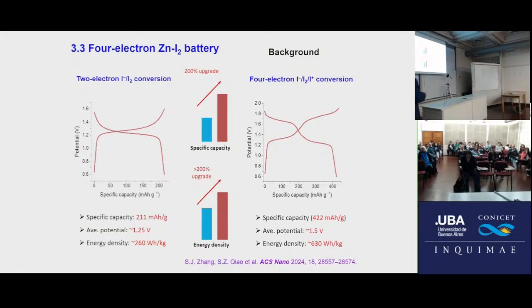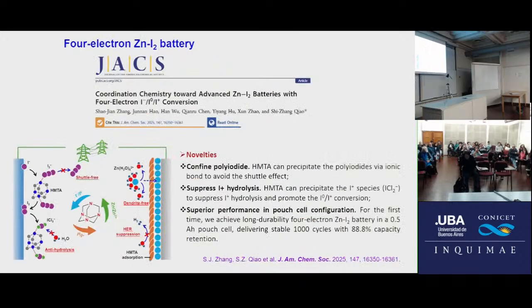However, if we achieve this conversion, this is a 4 electron conversion. This means from iodine minus to iodine plus. In that case, you can see these two platforms. You can see here is a 4 electron conversion. You can see this capacity is double, right? The energy density is much higher than double. Okay, the problem is it's very difficult to achieve this conversion. So in this public work this year, actually we achieved this conversion already.